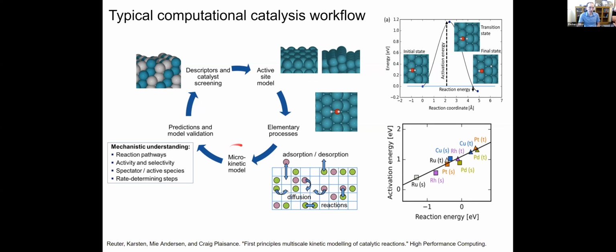And then once we have this microkinetic model, we can analyze it with things like sensitivity or rate determining step analysis to try and figure out what are the right descriptors or what are the rate limiting steps. And with that information, we go back to the beginning, develop new descriptors, screen again, and continue this process in a loop. And this workflow is relatively straightforward, right? It's been successfully applied in a lot of different applications of catalysis over the past 20 or 30 years or so. But it is very expensive and there's a lot of complexity.